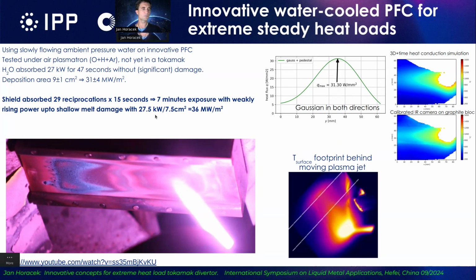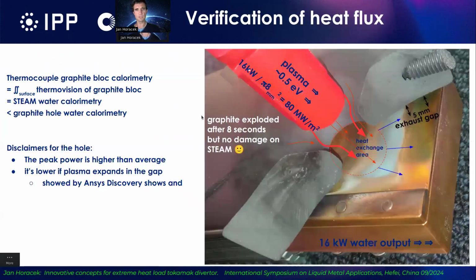In another experiment, it was the first experiment we did. In another one, we did it better. And we could do 29 reciprocations with 15 seconds plasma. In total, it means 7 minutes exposure with weakly rising power up to shallow damage, where we extracted 36 megawatt per square meter. And then we did another experiment just a few weeks ago, where we believe we went up to 66 or even above 100 megawatt per square meter for quite a long time, for a few minutes. So that's what we achieved so far.